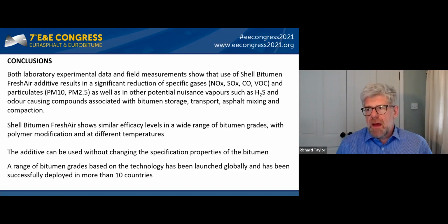So in conclusion, both the laboratory experiments and the field measurements show that the Shell Bitumen fresh air additive results in significant reductions in air quality related gases, as well as other nuisance vapors such as H2S and odor causing compounds. We have similar efficacy levels in a wide range of bitumen grades. We don't change the specification here. This is an additive which doesn't change the properties of the bitumen or the asphalt. And since we've developed the additive, we've now gone on to commercialize the technology and launched in more than 10 countries. And so I thank you for your attention. I look forward to any questions you might have.